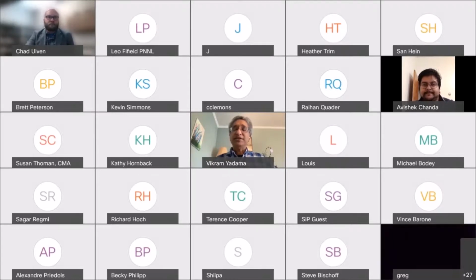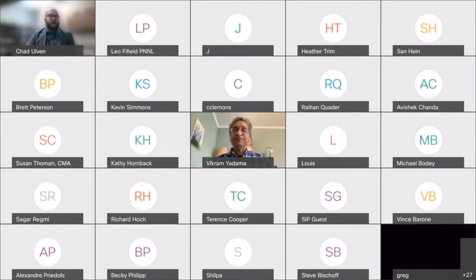Chad, there are other good questions here in chat. One is, what type of sizing needs to be applied to fibers to make them compatible with common resin systems? Yeah, that really depends on your resin, you match your compatibilizer with your resin. So for instance, when we're compounding into polypropylene, we usually use a maleic anhydride grafted polypropylene. If our matrix is polyethylene, we use a maleic anhydride grafted polyethylene. And we've even made some of our own MAPLA, so maleic anhydride grafted to PLA. When it comes to some of our thermosetting resins, that's where we try some silanes. We found them to be somewhat effective, so that you can get that bonding of that very hydrophilic surface to that traditionally very hydrophobic matrix. You need that compatibilizer, and it needs to be strategic for the particular polymer that you're working with.